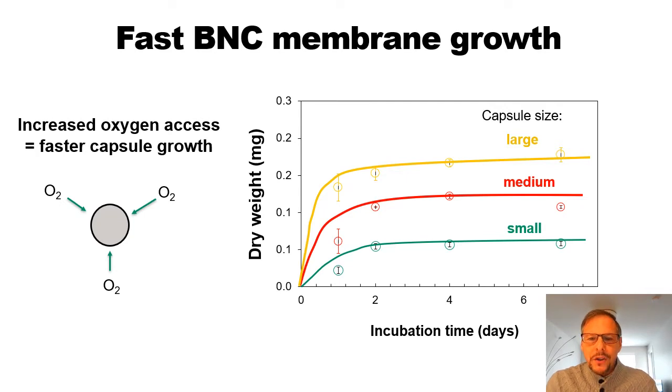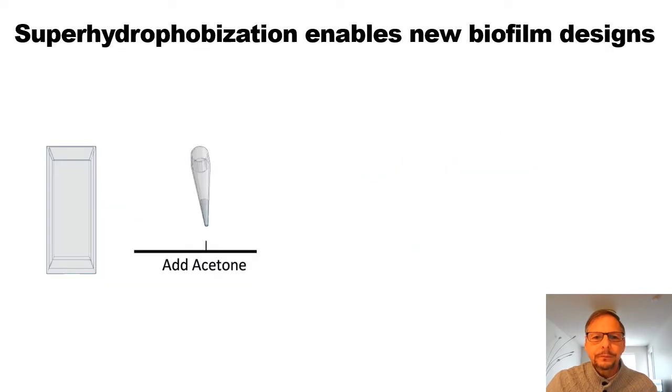And also you appreciate that depending on the size of the droplet of the culture medium that we deposited on the surface, you can have larger or smaller particles. In all cases, what we're using is oxygen or air that is entrapped at the interface for the microorganisms to be able to undergo the aerobic process of producing the cellulose as a biofilm.